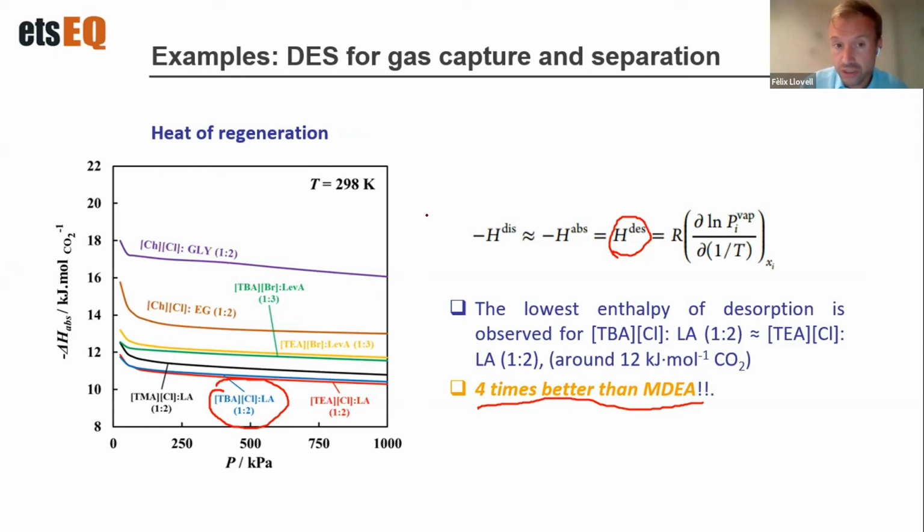There is a third one which is less clear, and for me this is a drawback of the equation, which is called the correlation length, because this L comes from the combination of two additional compounds that are combined in one. Then there is not a clear pattern for this one, which at the end means that you always have to fit it, and you have no clear idea of what you are going to get. We got very good results for systems up to polymeric systems. And we also got very good results for complex systems, such as refrigerants and hydrogen bonding mixtures.